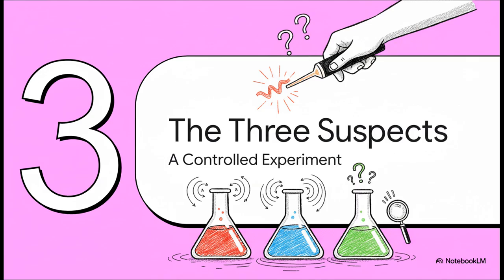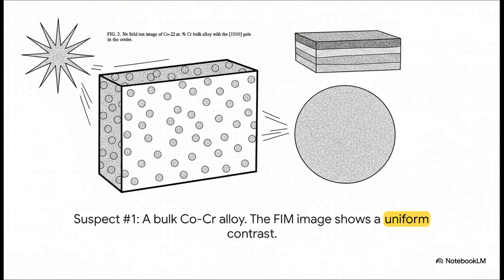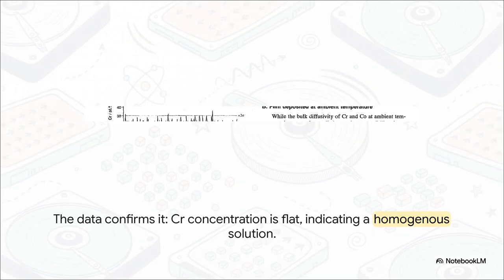It was time for a lineup. They prepared 3 different samples, our 3 suspects, to figure out exactly what the heat was doing. Suspect number 1 was just a standard, solid chunk of the cobalt chromium alloy, a bulk sample. And as you can see, the picture from the atom probe is, well, it's totally uniform. This tells us that in its natural state, the atoms are all just randomly and evenly mixed together. This is our baseline. And the data backs this up big time.